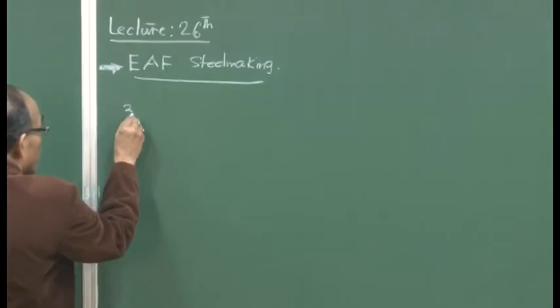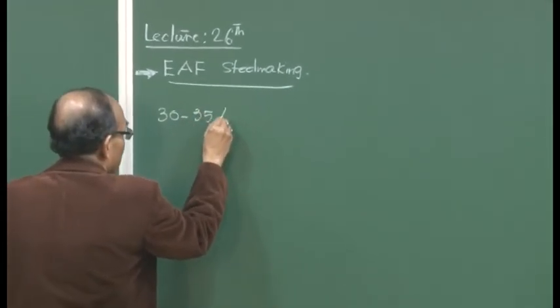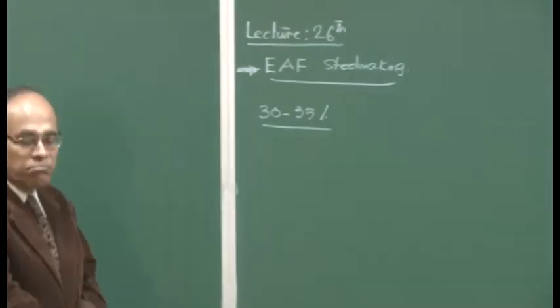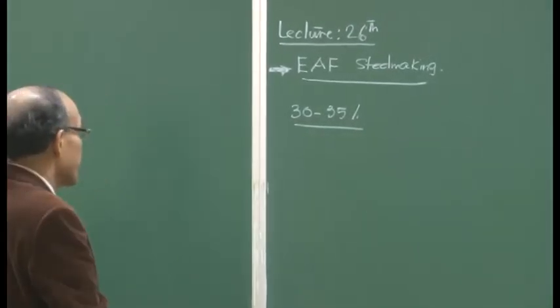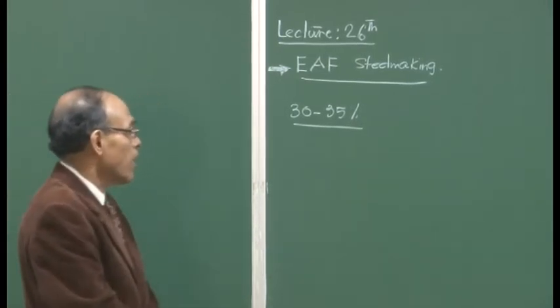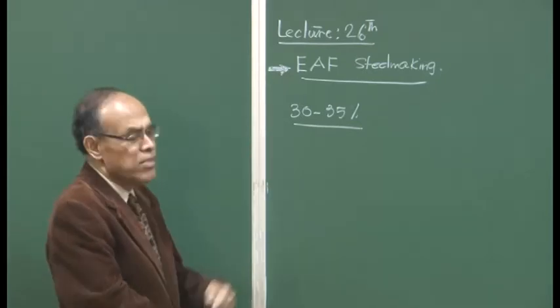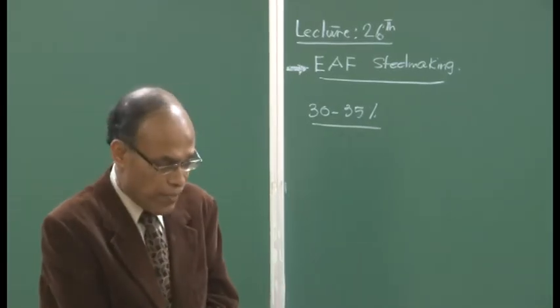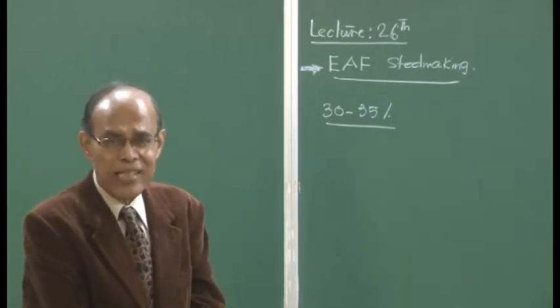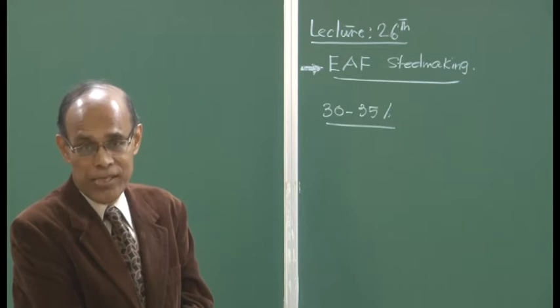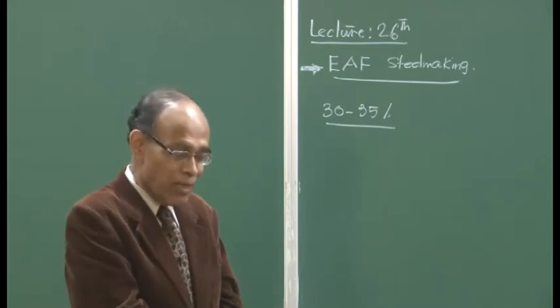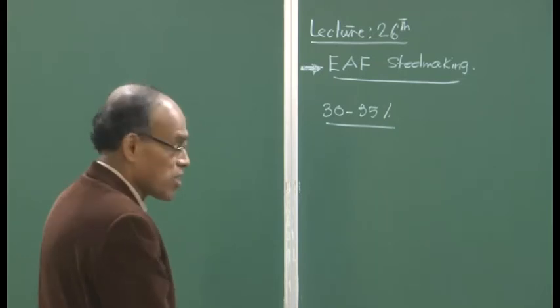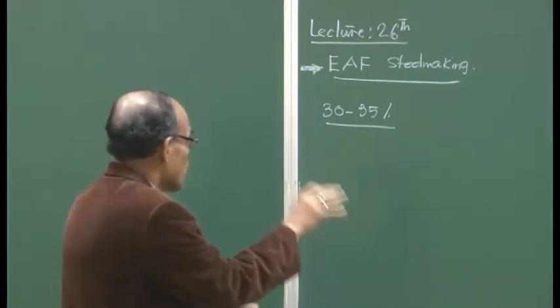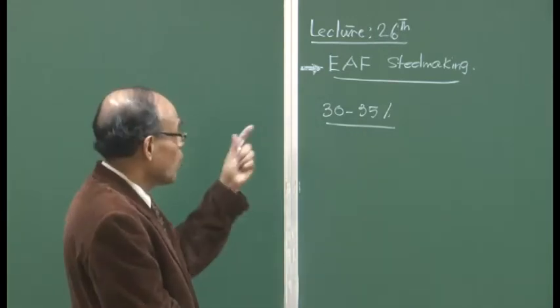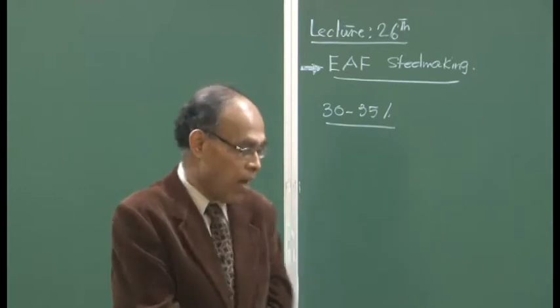And we know that, as I have said, 30 to 34%, I would say 35%, of the global steel making is through the electric arc furnace technology. And arc furnace, of course, is used in the steel industry for steel making. Arc furnace also is used just as a pure remelting unit in many of the foundries, which want to process liquid metal. So, they do not do any refining, they do not do any processing, they just melt liquid steel in the arc furnace. So, that sort of a discussion we are not going to make. We are going to explore steel making in an electric arc furnace.